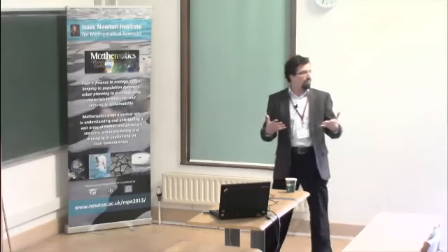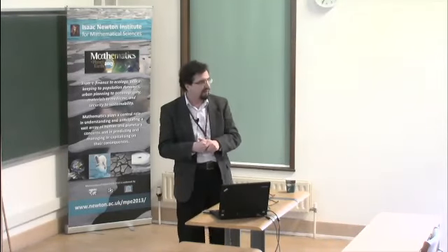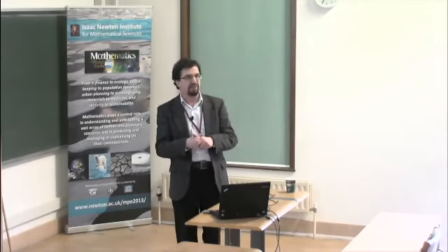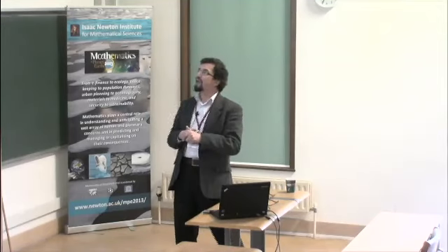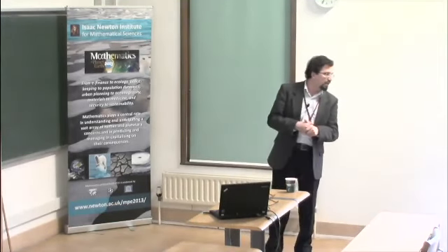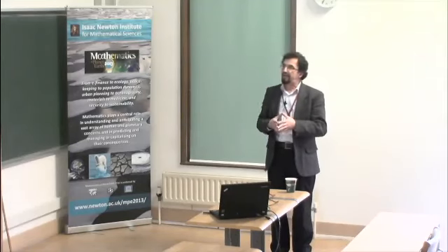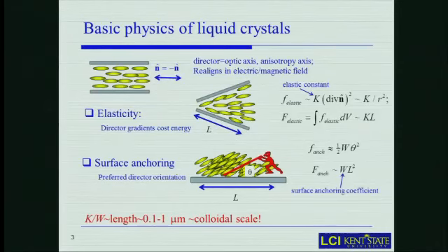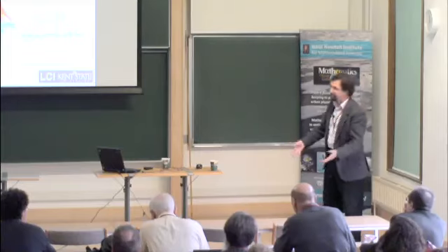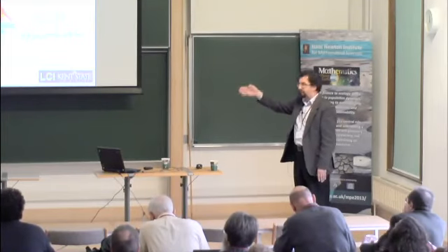For us, it's probably not that important to deal with the reorientation of this anisotropic fluid in an external electric or magnetic field. The two most important things will be the concept of elasticity and anisotropy of surface tension. So elasticity deals with the simple fact that whenever you want to misalign the director so that it's not pointing in some constant direction, whenever you would like to make a distortion like a splay with my fingers, you have to perform some work because the molecules would like to be parallel to each other.